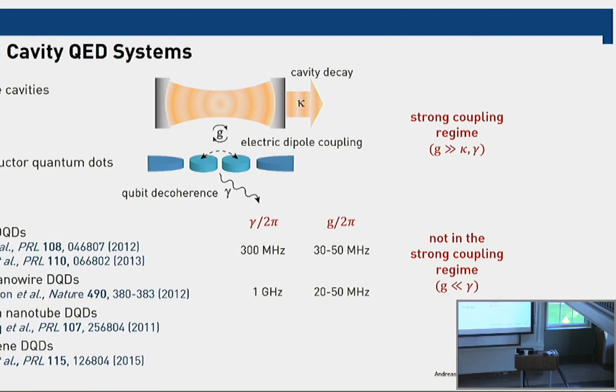And that was a bit surprising to see, because the material systems were very, very different. The decoherence rates were almost uniformly in this range, independent of whether it was indium arsenide nanowires or graphene or whatever else, while the coupling strengths themselves were quite sizable. The coherent coupling rates g were on the order of a few tens of megahertz or maybe even 100 megahertz, which are typical rates at which in superconducting circuits you easily achieve the strong coupling limit, because in superconducting circuits the decoherence rates were a lot smaller.